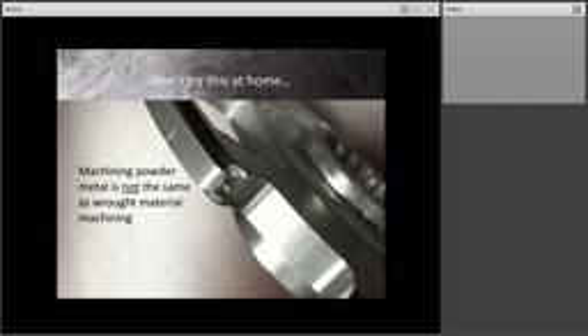And don't try it at home. Powder metal is not like machining wrought material. It has its nuances. You can have issues with damage or breakage that you wouldn't see on a standard component made out of wrought material, simply because of the nature of powder metal, where there's a degree of porosity in the component. Effectively in powder metal, you have components made of particles of powder separated by small voids, so each of those particles becomes a hard component to machine. Each time a machining insert, for example, hits those small particles, it's like a hardened strike on the part, which can break down the inserts. That's something that we at Syntris have certainly learned over the years, and we feel that we're as good at turning or machining powder metal components as anybody in the world.